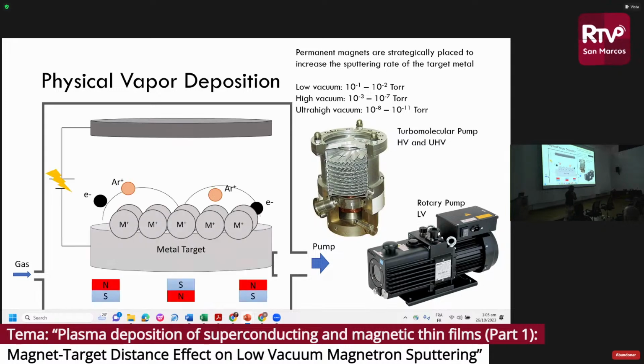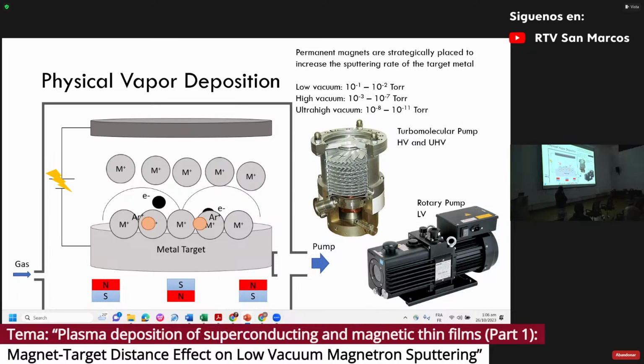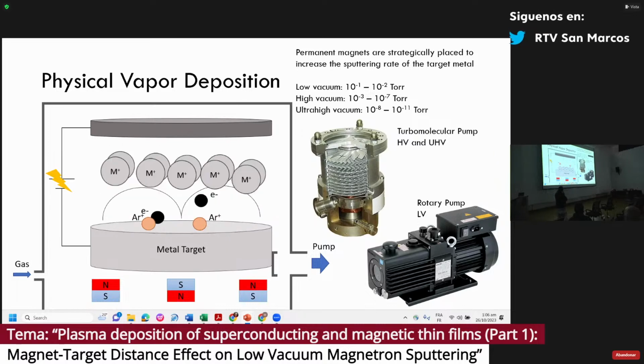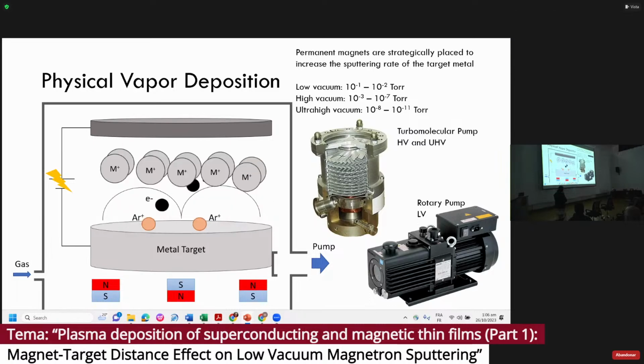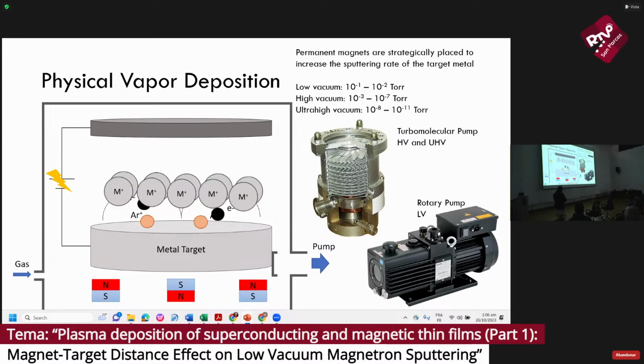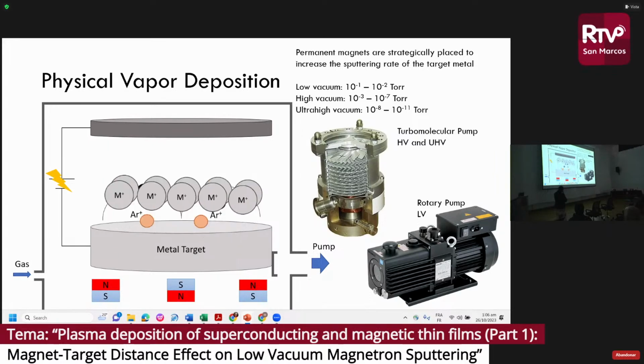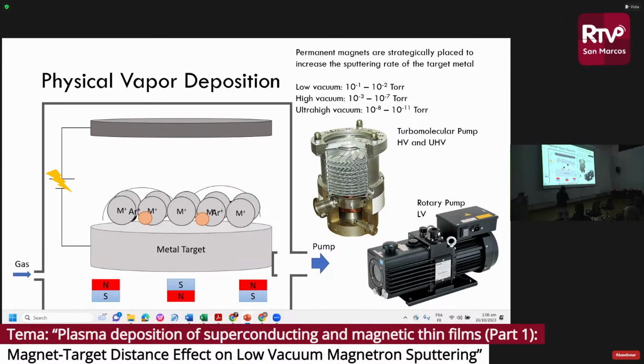So this is how a magnetron sputtering works. We have a metal target, and then we have magnets underneath the metal target. What happens is that there's going to be a confinement. Now, if we introduce argon gas into the system and then create a bias between the metal target and the grounding, for example, we would activate argon to become argon ions. And then the electrons get trapped in the magnetic field, thereby the argon ions attack the metal target. If we do this for a long time, then we get to harvest the metal target and it gets deposited onto our substrate. Sometimes these metals will get deposited on the side of the chamber. So that's how magnetron sputtering works.